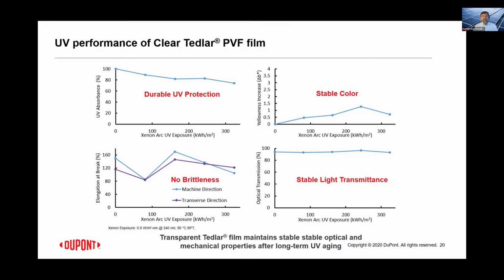The top right over here shows that the material, which is a polymeric material, does not change color appreciably over this period of time. Again, it gives us the confidence that the material is not changing that much. The material doesn't get brittle on the bottom left over here. That's what we are seeing. And this is just the film, by the way. We are not at the backsheet stage. I'll take you through the film and then over to the backsheet and finally through the module stage to show how we are tracking the progress of the stability and durability of the material through the different phases of getting it integrated into the module.